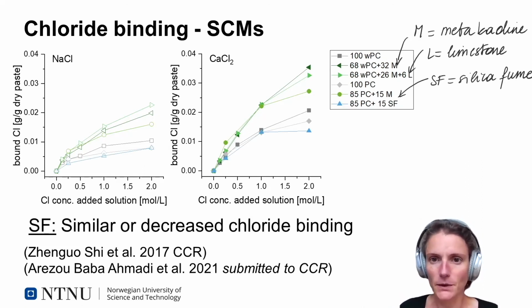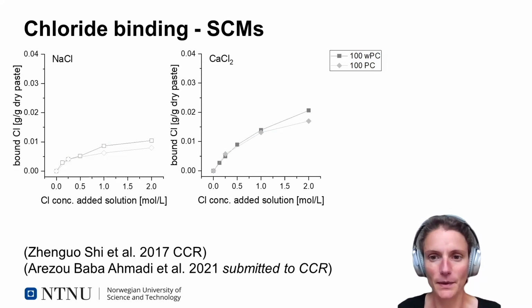When we add silica fume to the system, for example, 15% silica fume, we see a similar or decreased chloride binding. It's also some chloride exposure.